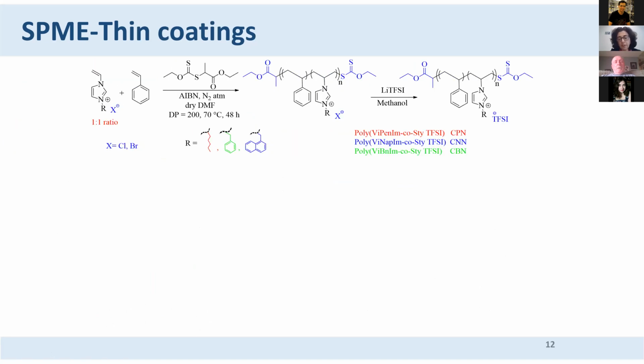For the thin fiber, we had the collaboration with an Indian group that synthesized the polymer for us. And this is a copolymer, as you can see. So one of the monomers is an ionic liquid and the other is not. And we are going again to play with this side chain. It can be an alkyl chain, a benzene group, or a naphthyl group.